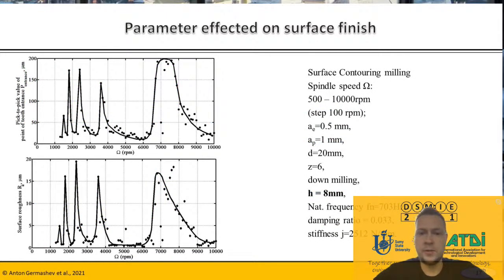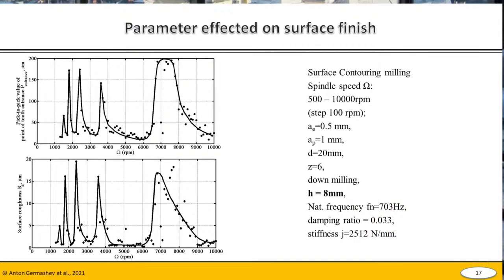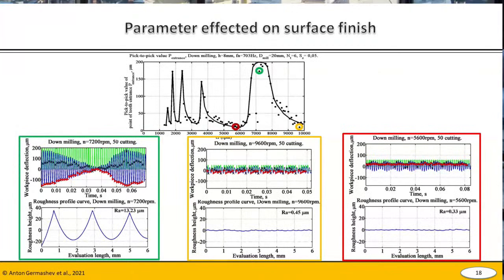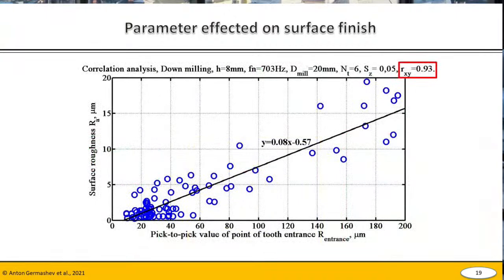Here are shown some experimental results and surface quality. We are able to observe here that if we have a big difference, a big peak-to-peak value of the point of tooth entrance, the quality is significantly reduced. So this is a real experimental test. And the next slide, please. This also shows some examples where we reached good cutting conditions and where we have the big value. The next slide, please. Also, we made a correlation analysis to prove our approach. So we're able to observe that the parameters chosen by us show an influence on the surface finish. The next slide, please.